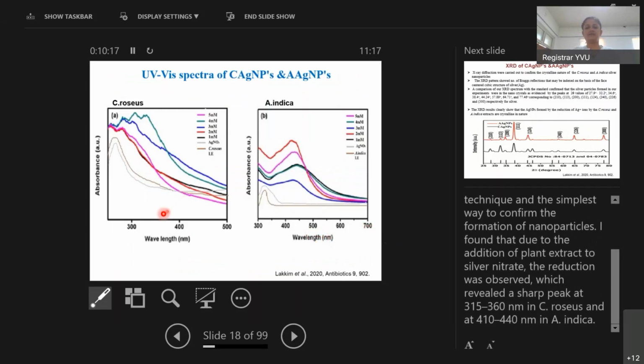The reduction was observed in Catharanthus roseus in the 315 to 360 nanometer range, with 1 millimolar to 5 millimolar. The different colors of the concentration gradients represent the absorption. This is the Azadirachta indica UV visible spectrum, with the colored peaks of 1 millimolar to 5 millimolar. The reduction was observed at 410 to 440 nanometers in Azadirachta indica.